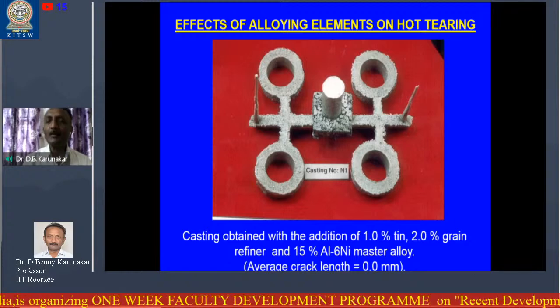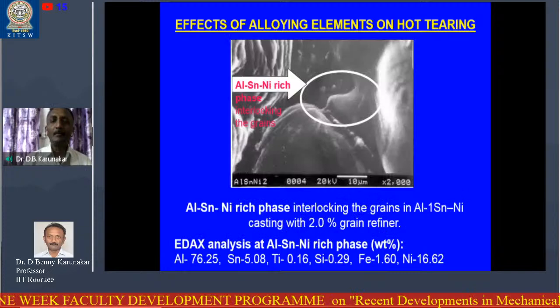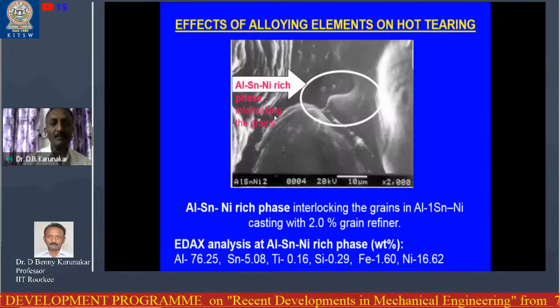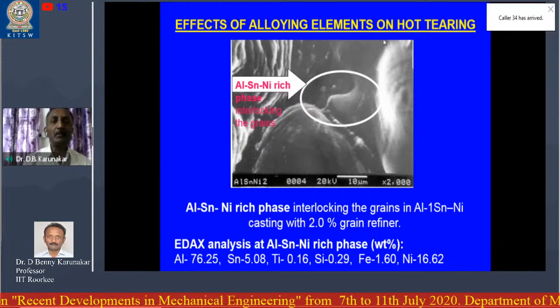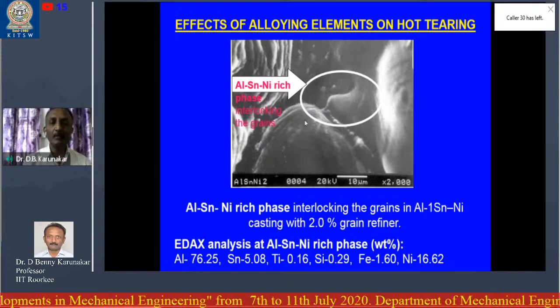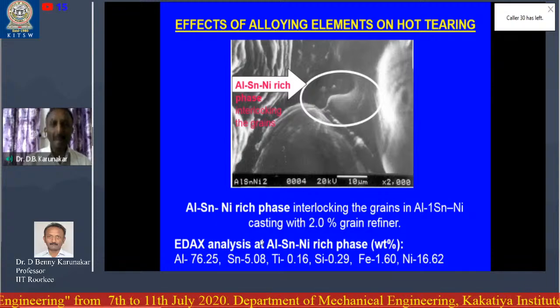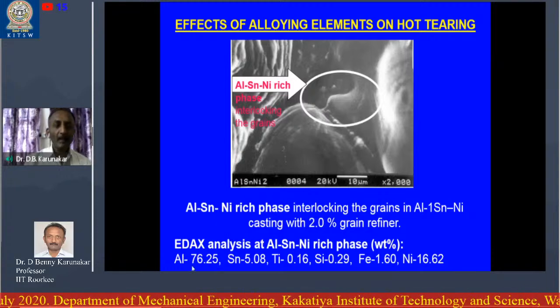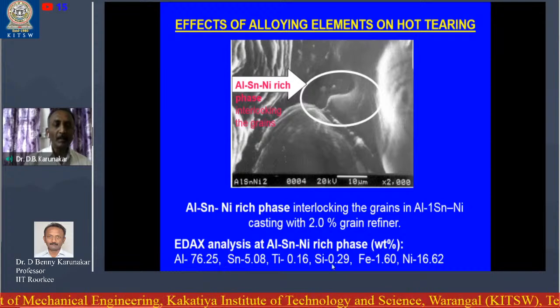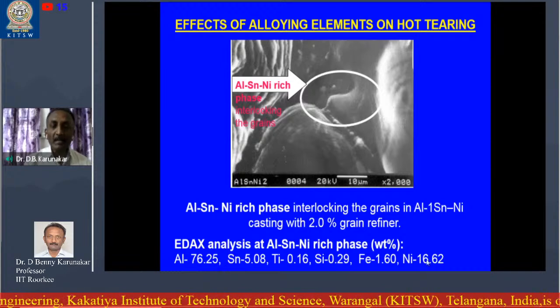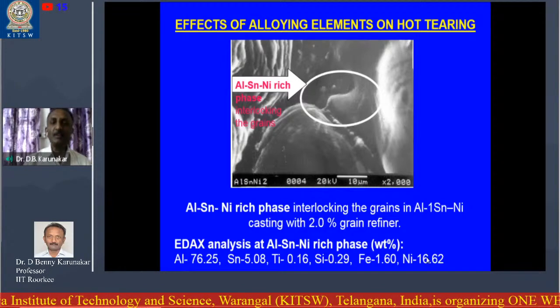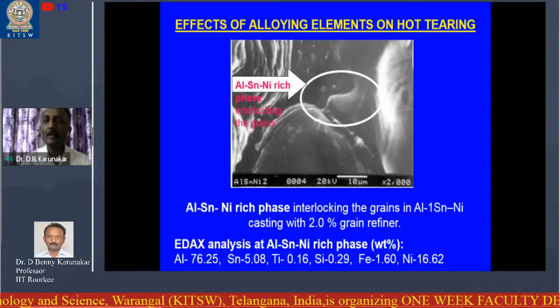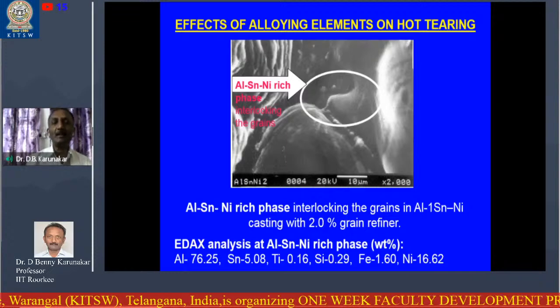Why was it removed? When we investigated under SEM, we again see a hard aluminum-nickel rich phase here. We analyzed it under EDAX, and you see tin proportion is 5% and nickel is 16%.